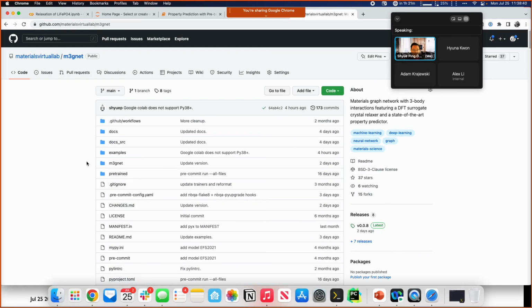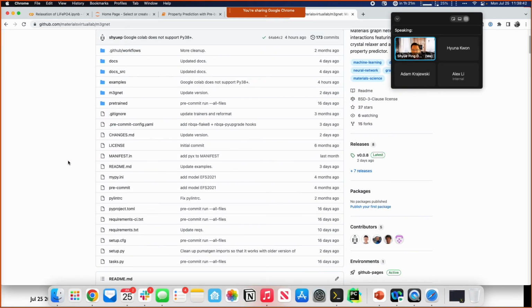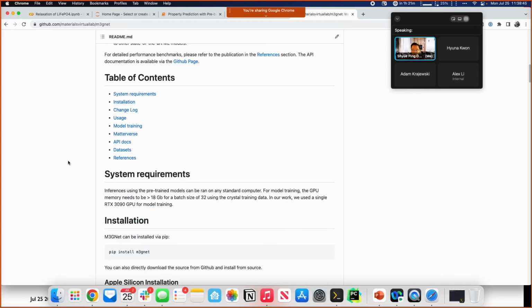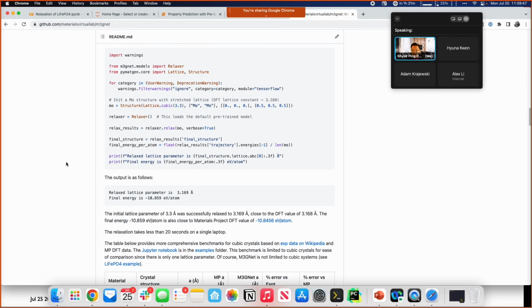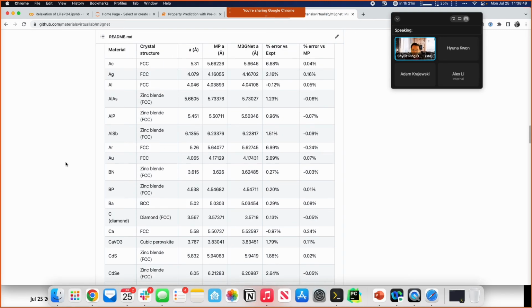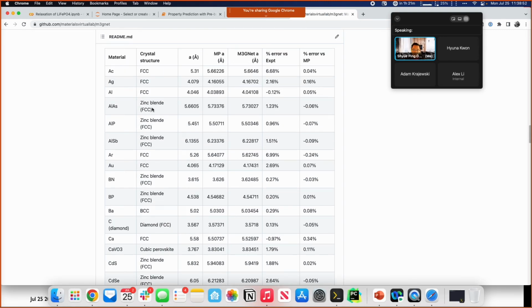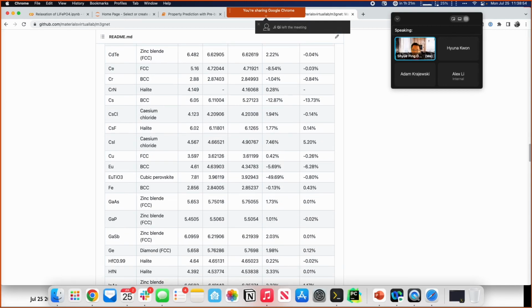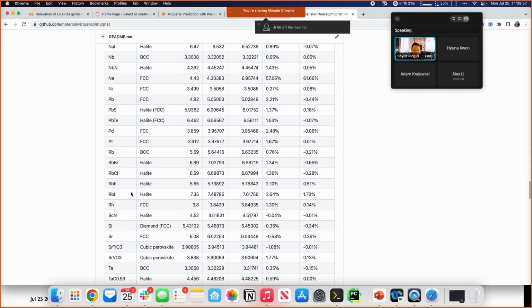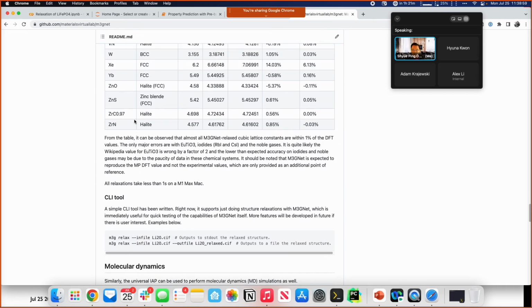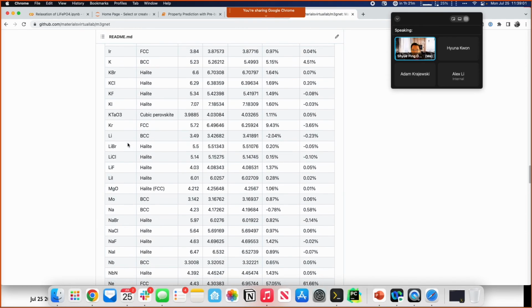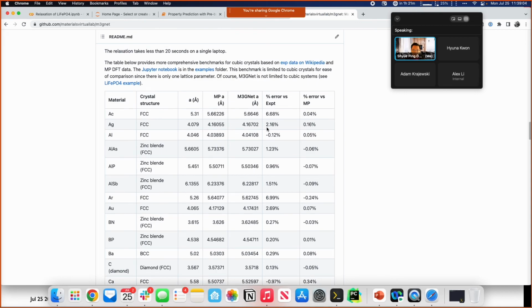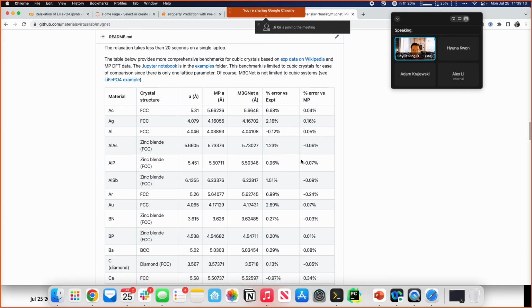because one of the things that people are skeptical about is, well, if you have a potential for the entire periodic table, really how well can it work, right? So to actually prove to everyone that it will work, we took a set of about 90 cubic crystal structures. Okay, so all these are cubic crystals, and they have DFT relaxed crystal lattice parameters, as well as experimental lattice parameters. And we used M3GNet to relax all these crystal structures, right?